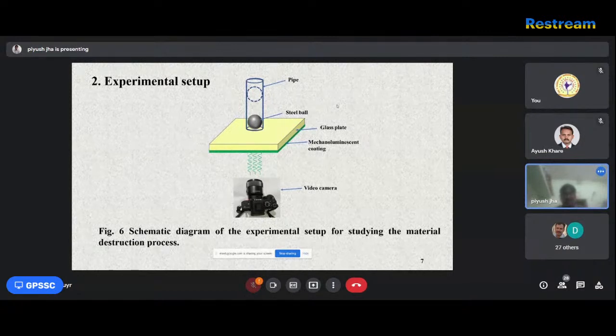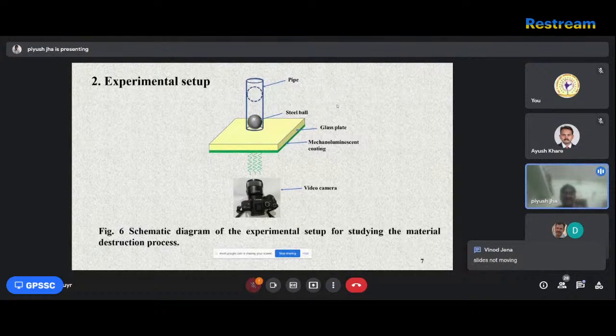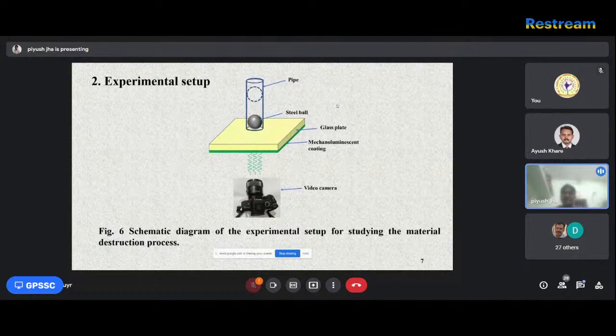The ML images are recorded by a Sony Alpha digital camera. The ML sensor was first irradiated by a light emitting diode of wavelength 365 nanometer for 1 minute and kept under dark condition for 5 minutes. When the steel ball of mass 66 gram is dropped from a height of 50 centimeter, it creates damage in the glass plate. In this experiment, we captured a fracture generation video by the Sony Alpha digital camera.